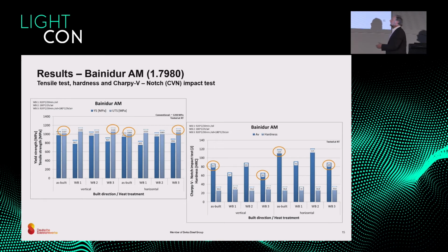And in the as-built structure, you get a Charpy V impact toughness above 80 joules. It's even more than you actually have in your cars. So you can use this material in the as-built condition. You can do heat treatment, or you can use this material without any heat treatment. With heat treatment, you get nearly the same results as if you use bulk material.